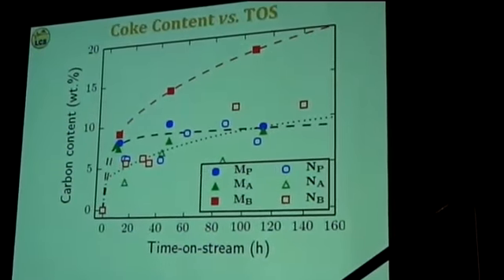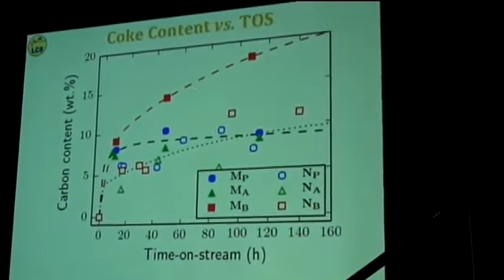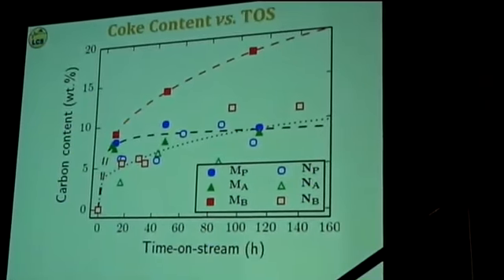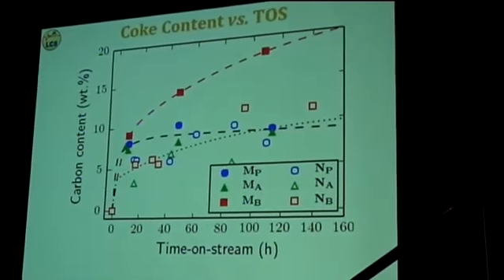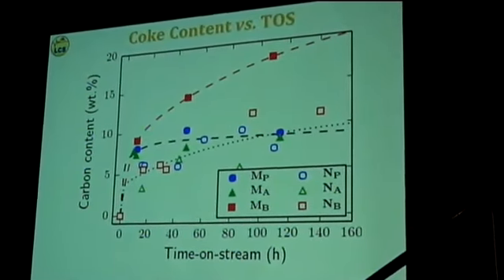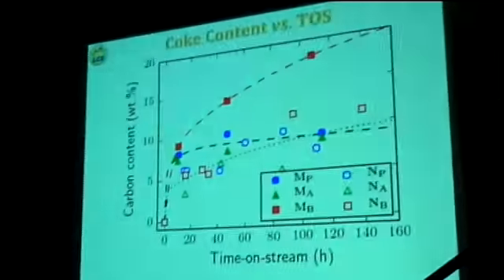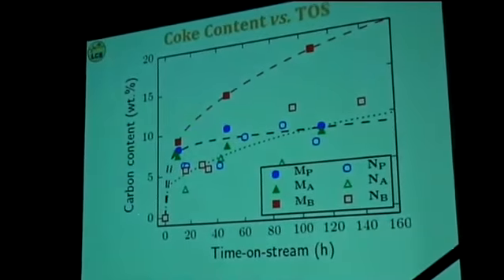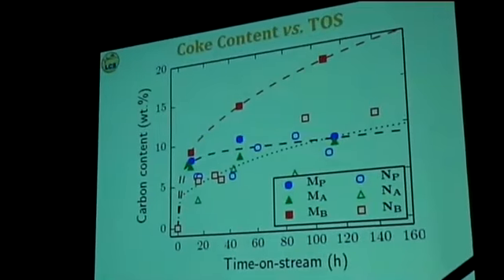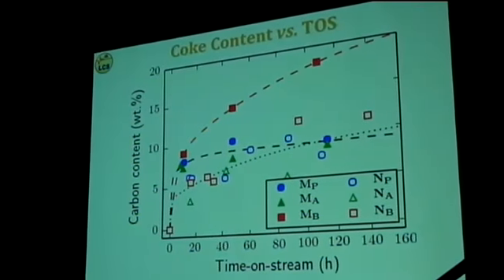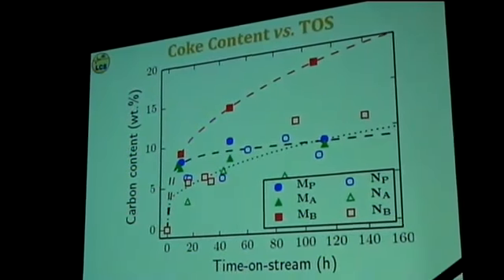The explanation is that, in fact, this material contains an extremely large number of hydroxyl defects, and these defects are just traps where coke molecules are falling, and coke is accumulating very fast. So again, if you look a little bit closer here, although we reach the same level of coke, the speed at which you reach the same level of coke is faster on the micron-sized crystal than on the nano-sized crystal.